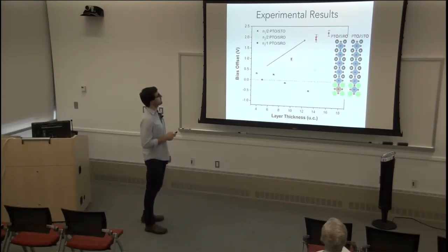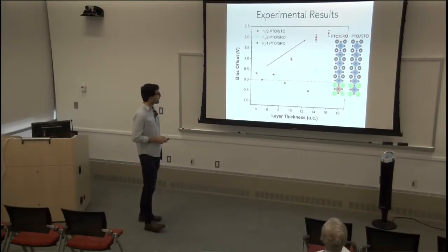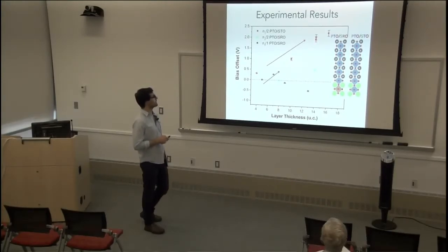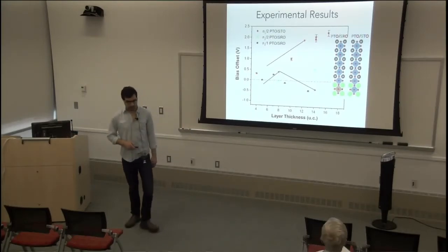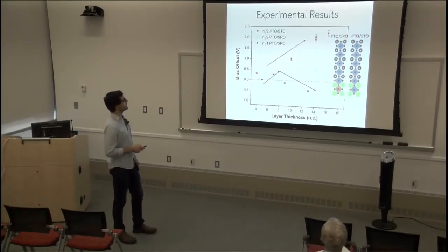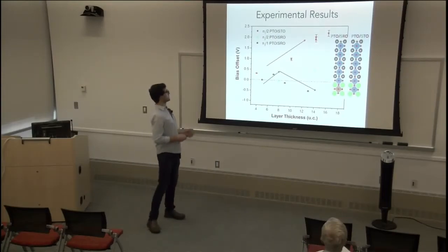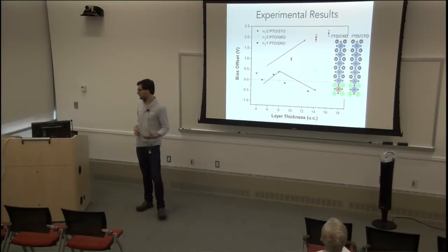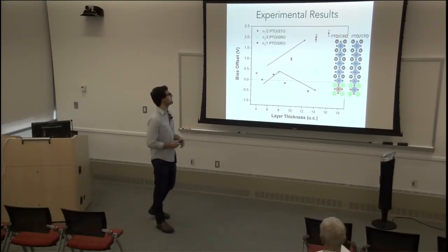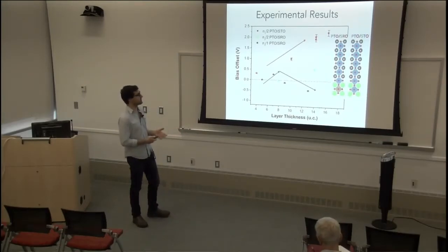And for lead titanate strontium ruthenate, which is here on the left, as I increase the number of lead titanate unit cells, initially you have an increase, the same as lead titanate strontium titanate. But then the bias goes negative and decreases with increasing lead titanate layer thickness. These materials are quite similar, but they have completely different trends with lead titanate layer thickness. At this point the experimentalists were stuck, and they needed input from the theorists, because we can go and do some sort of first principles calculations.